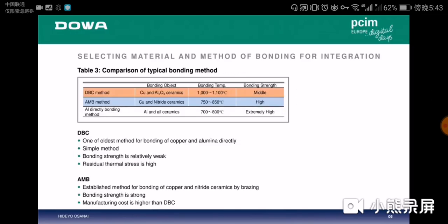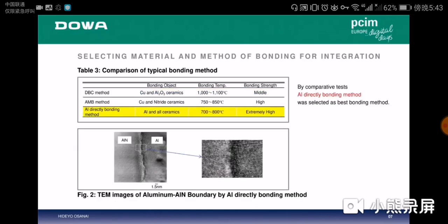Table 3 shows a comparison of methods for bonding metal and ceramics. The DBC method and the AMB method are very famous, and this sheet shows those features. By comparative tests, the aluminum direct bonding method was selected as the best bonding method regarding bonding temperature and bonding strength. A benefit of this bonding method is that various 3D product shapes can be easily produced by the design of the mold. Another benefit is that the bonding strength is extremely high.